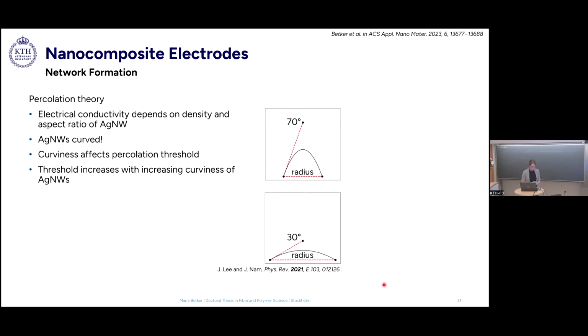Another important factor is the network formation. And from percolation theory, we know that the conductivity of a nanowire network actually depends on the percolation. So this means it depends on the number or density of nanowires in the system, but it also depends on the aspect ratio. Yeah, it makes sense. The longer your nanowires, the higher the probability that they will cross or find each other in the system. And in this publication here, they investigated the effect of curviness, because actually the longer your nanowires are, the more curved they will be in your electrode.